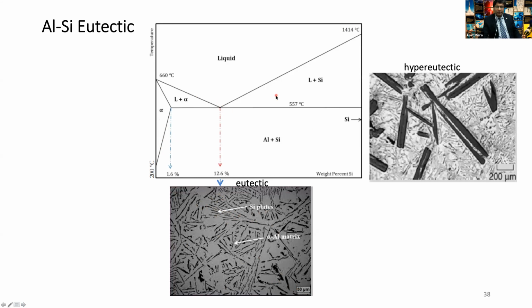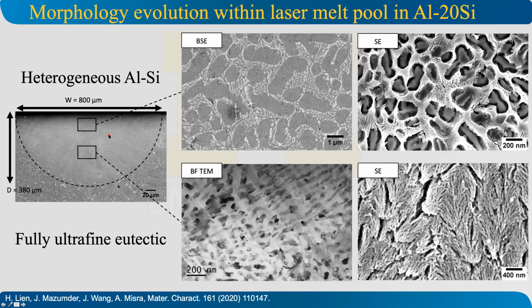If you go on the silicon rich side, so you get hyper eutectic structure. So first silicon phase will form. So you see here those large dark regions, very coarse, very brittle silicon, and in between the remaining liquid will then solidify as by this eutectic reaction of almost pure aluminum and almost pure silicon. Essentially pure silicon, very fine scale structure that can form here. But still fine scale meaning maybe 10 micron or so in that range. What happens under laser is that the cooling rates can be thousands to 10,000 Kelvin per second, and the structure completely changes.